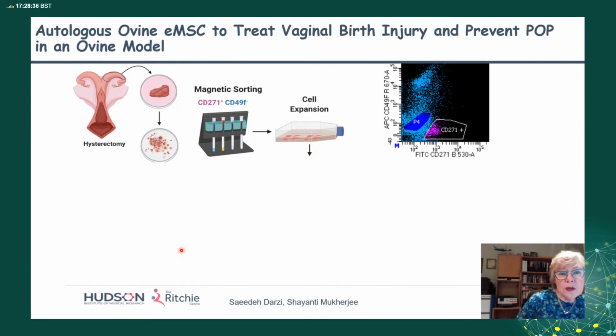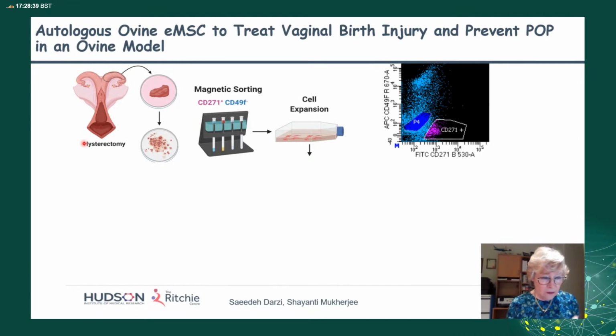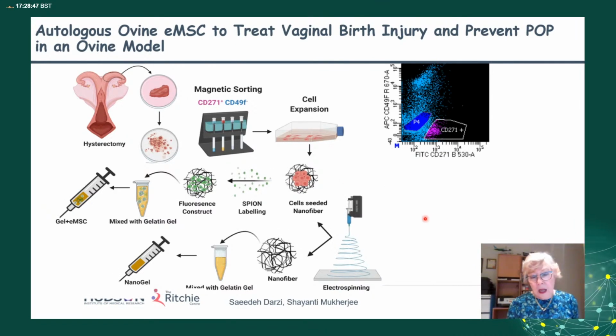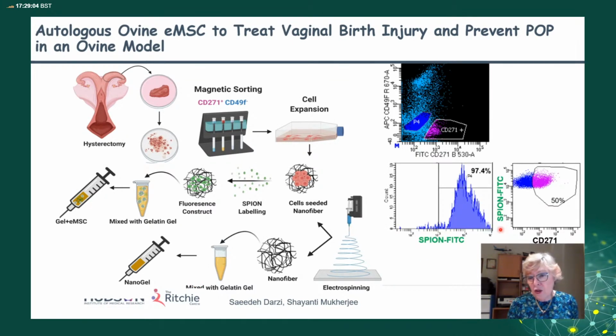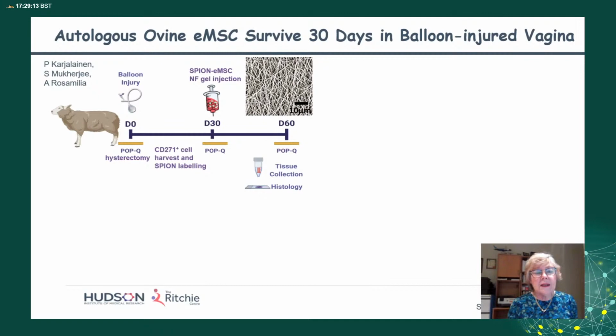Now, to treat the sheep, we had to do a hysterectomy of the individual sheep, harvest their cells, purify the CD271 positive cells, and expand them in culture. We then seeded them onto the nanofiber material labelled with the SPIONs, embedded that in gel. This is all done in a format that is injectable, and similarly without cells for the nanomesh on its own. And this just shows that we were able to label the cells very well with the SPIONs, and we selected the highly expressing CD271s. Now here it just shows what I've already just said.